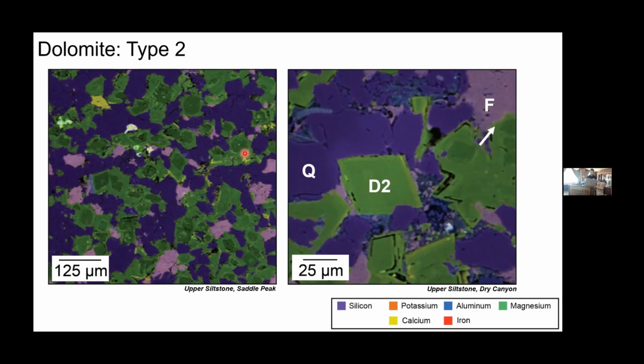And looking to the EDS map here on the left, zooming out to give you a better view of how this all fits together, one phase relative to another, you can see that the type 1 dolomites are typically the most abundant, but you can see a number of areas that have the type 2 crystals only and not the type 1. But again, these are the phases that comprise a majority of the rock volume, typically between 50 and 61%.